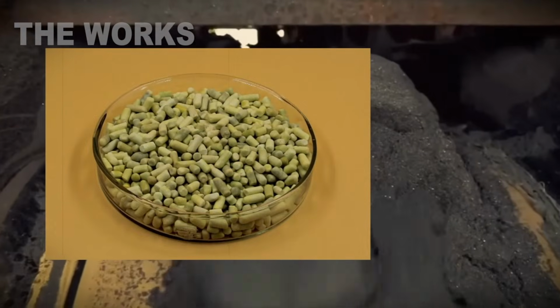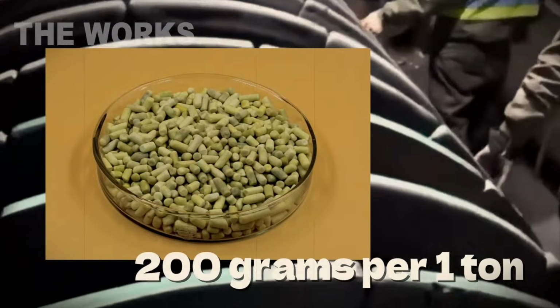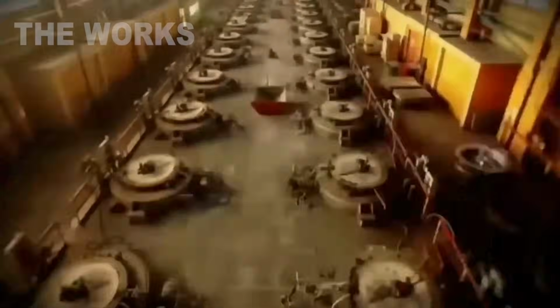Flotation enrichment. Ore powder gets mixed with water, creates a slurry. Solid concentration, 30%. Add reagents. Potassium xanthate, 7 ounces per ton of ore. Pine oil, 1.8 ounces per ton. Xanthate makes iron particles hydrophobic. They repel water.